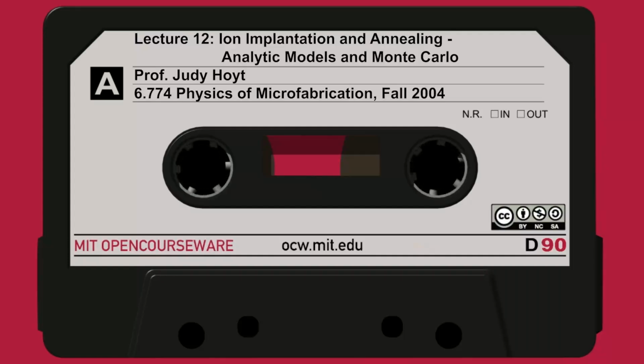So now on slide 35, let me summarize. We saw that ion implant is the preferred process for introducing dopants. It has excellent control. It's very reproducible and uniform. The key parameters: energy of the incoming beam, the dose, the tilt of the wafer with respect to the beam, the rotation of the axis of the wafer, whether there are any masking materials on the wafer. Controlling the temperature of the wafer during the implant is actually somewhat important because it'll control the damage that gets done to the crystal to a certain extent. The dose rate, the beam current, how quickly are you putting it in? Actually, the dose rate determines how much you heat the wafer up, and that's important.